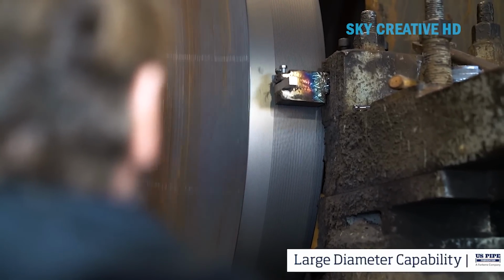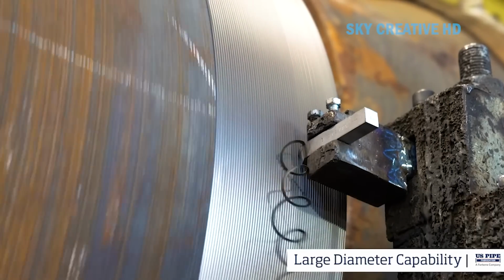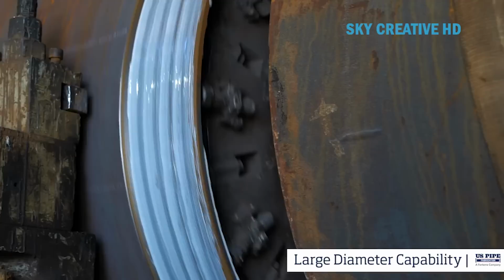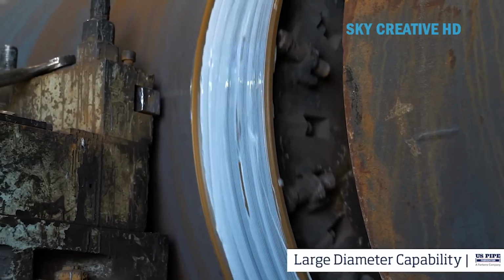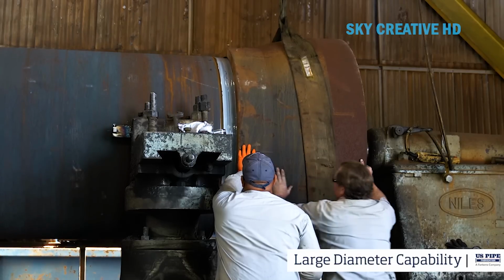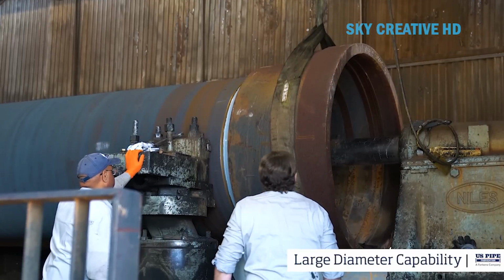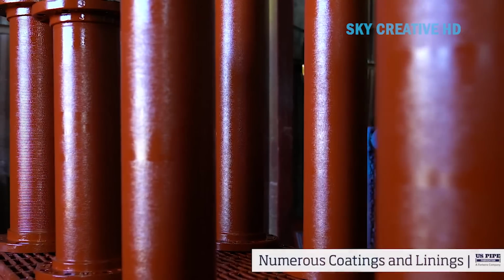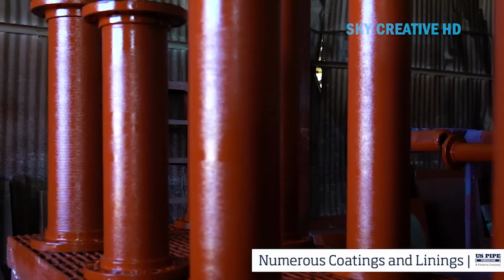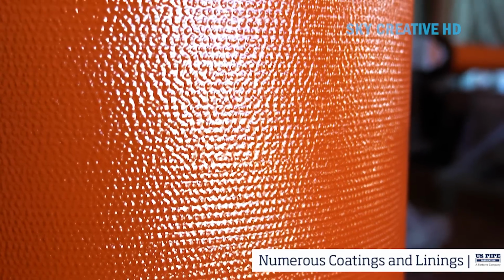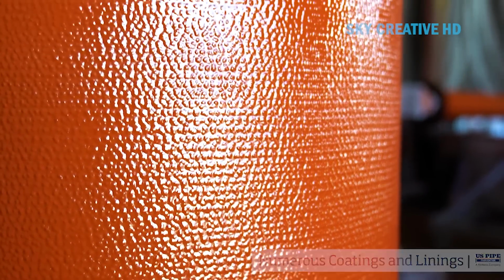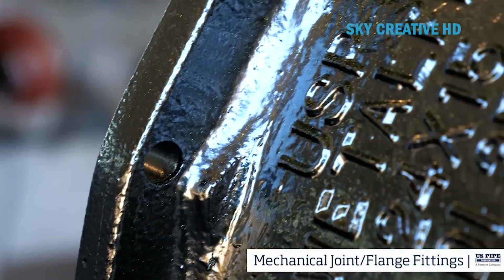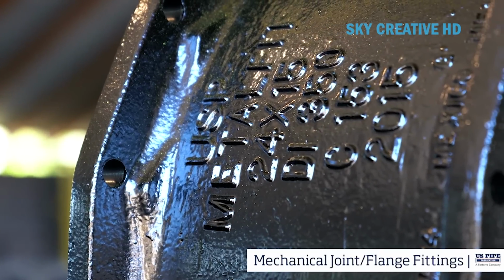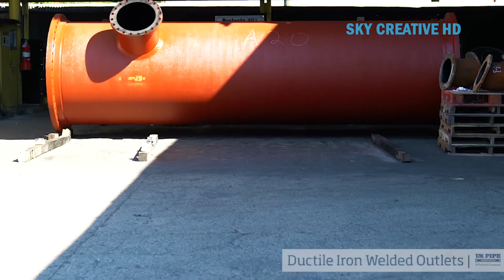Coating is crucial for corrosion protection and can involve various methods, such as epoxy coating, powder coating, or galvanizing. Automated coating lines ensure uniform application and consistent thickness. Hydrostatic testing is the final step, where the assembled pipe system is subjected to high pressure to verify its structural integrity and leak tightness. This test ensures that the fabricated piping system can withstand the intended operating conditions.